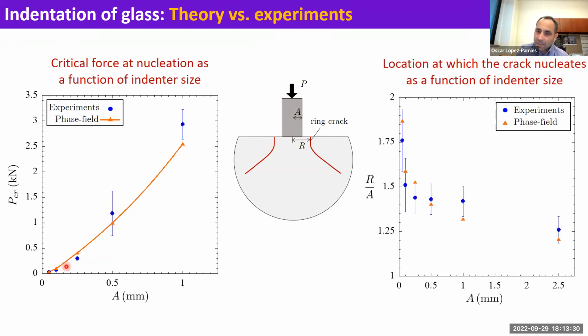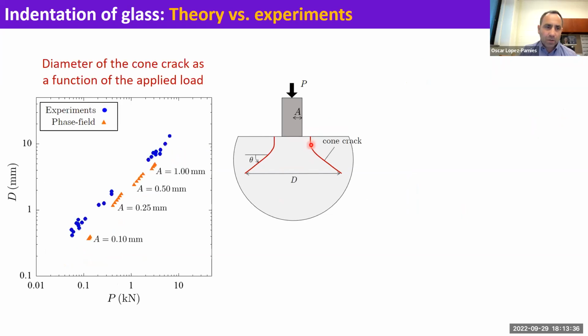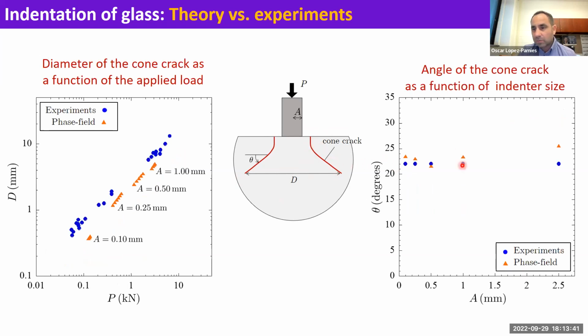These are other quantitative comparisons for the location at which the ring crack appears. And this is for the propagation, right? The diameter of the cone crack and the angle at which the crack propagates. So all of them seem to check. And so we are pretty pleased with these comparisons because they suggest that the equations describe reality.